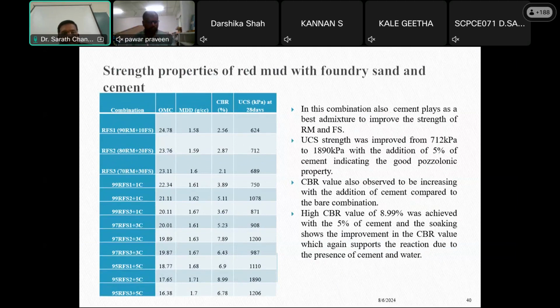Next one is red mud with foundry sand and cement. In this combination also, cement plays as the best admixture to improve the strength of red mud and foundry sand. UCS strength was improved from 712 kPa to 1890 kPa with the addition of 5% cement, indicating good pozzolanic property. The CBR value was also observed to increase with the addition of cement compared to the bare combination, and the highest CBR value of 8.99% was achieved with 5% cement. The soaking shows an improvement in CBR value, which again supports the reaction due to the presence of cement and water.